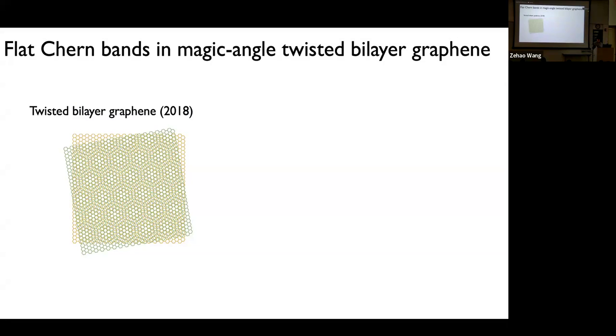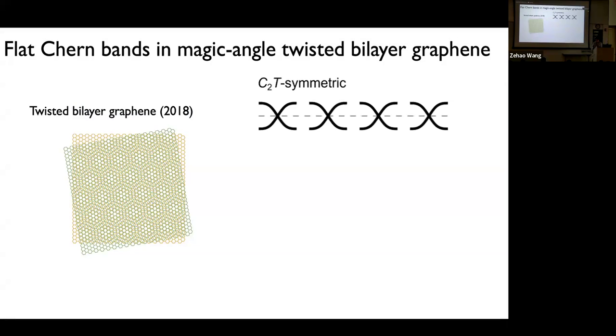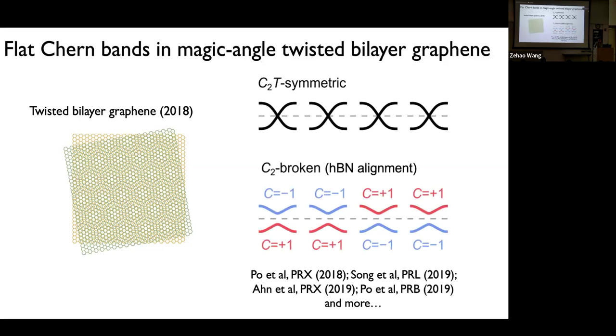And for the purpose of this talk, what you need to know is this system is described by these Dirac cones, and all the symmetries are preserved. And you have 4 of them because you have spin and valley degeneracy. And Eva told you yesterday, if you are able to break some of the symmetry, for example, break the C2 symmetry, which can be done by aligning the sample with the hexagonal boron nitride, then you can actually gap them and generate bands with finite Chern number. And this was immediately recognized soon after the discovery of correlated states and superconductivity in twisted bilayer graphene.